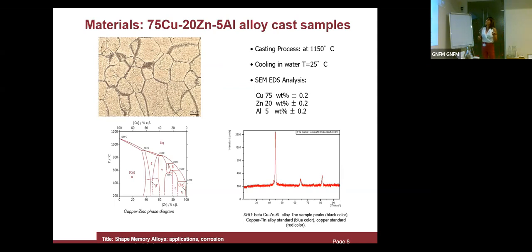This image is really interesting because here we can see the grain of our alloy. The grain is characteristic, and here we have the interface between the grains that is important to analyze because it's a preferential site for corrosion, because we can consider it as a defect. So it's an interface where we have high energy. So the corrosion processes are really activated. It's a preferential site.